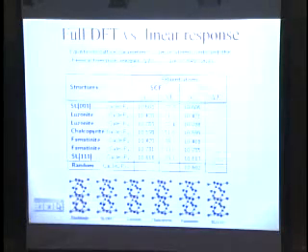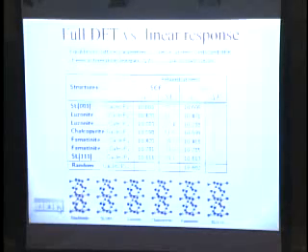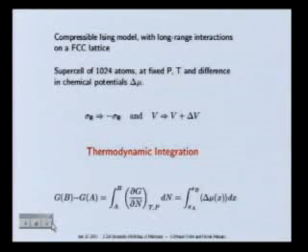And calculating this energy of mixing is absolutely inexpensive. It takes a nanosecond on your computer. You just basically sum with the appropriate configuration of variables the term with your interaction constants. This requires a full self-consistent calculation. So with this approach, you can calculate the energies of millions of structures that are very large, while with this, you can only calculate tens of structures that are reasonably small. So it's very appropriate to use the linear response term to then use one of these statistical sampling methods that you have seen with Professor Sider, and that again I won't go into detail because you have seen them partially and you'll see them over and over again.